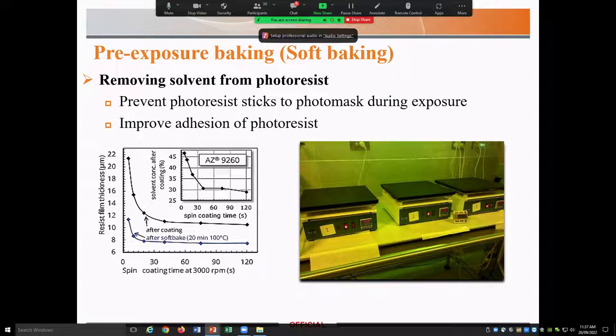So the next step after we coat the substrate with photoresist is soft baking, and this is to remove the solvent residues from the photoresist. This can prevent photoresist sticking to the photomask during the exposure and also can enhance the adhesion of photoresist. During the spin coating, the concentration of solvent rapidly sinks initially and then saturates to a value that depends on the thickness of the film, let's say, and also the solvent type.